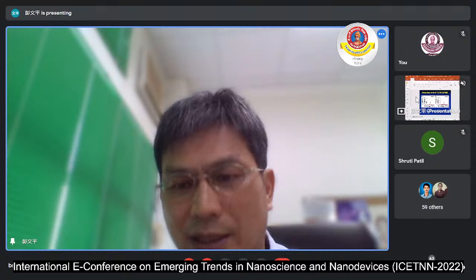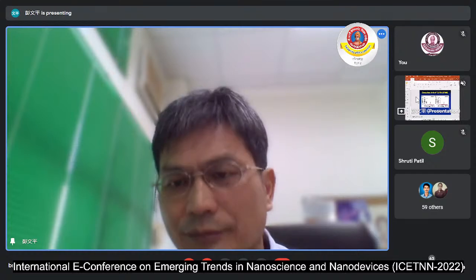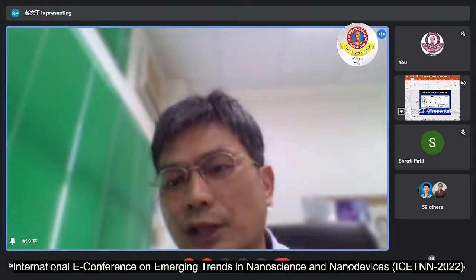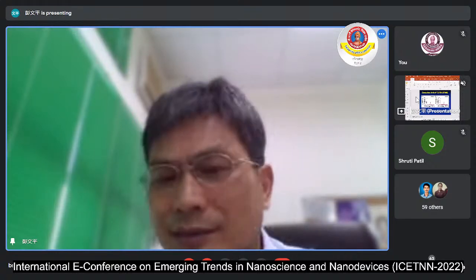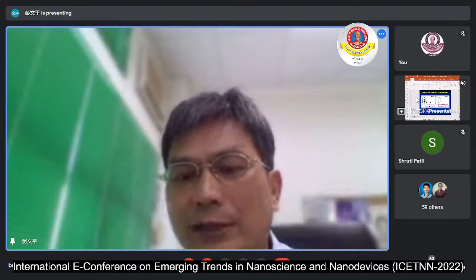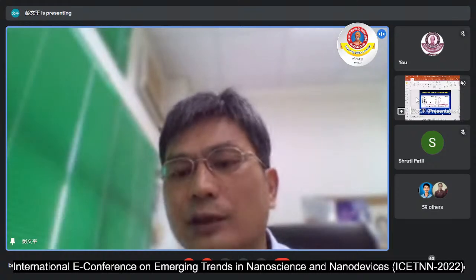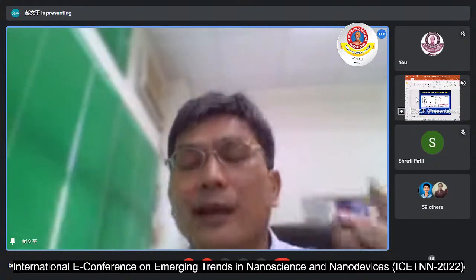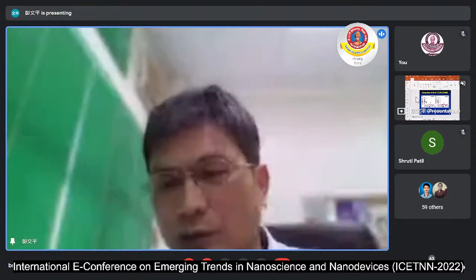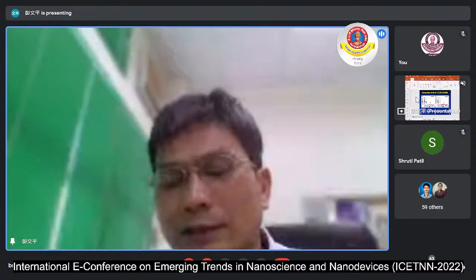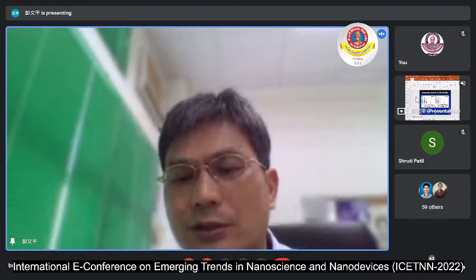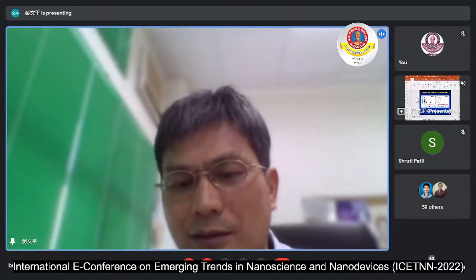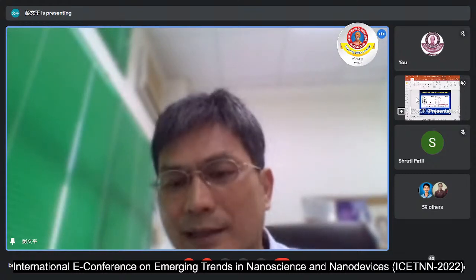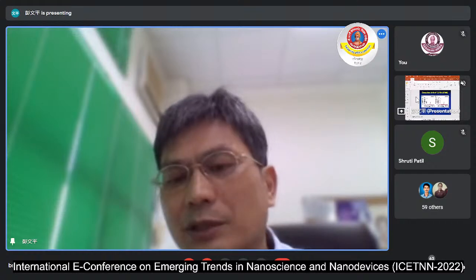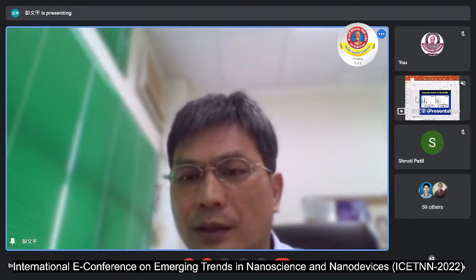This is the IgM signal. And we can reach 200 nanomolar. What does this mean? This means detection of IgM can reach 200 nanomolar, like 0.2 micromolar, which is better than the above instruments. As I showed you about the instruments, they're all greater than 0.5 micromolar. So that means using our homemade instrument, we have better sensitivity than the commercially available systems.